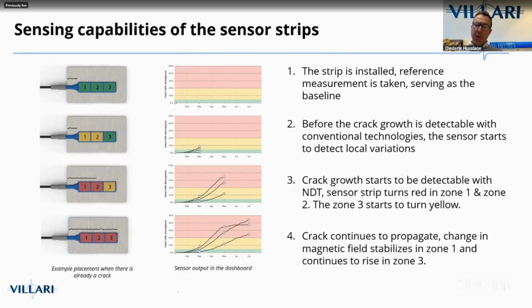On the third one, we see lines coming into the red, and that will be the time that you're able to see a crack, or at least have a high correlation that you will be able to see a crack. We are able to detect cracks from 1 millimeter onwards. Finally, the crack is fully propagated, all lines in the red, and the light will show horizontally unless the crack is either widening or deepening. When this happens, we can roughly indicate that the total length of the crack is around 4 centimeters. But this is a rough estimate.